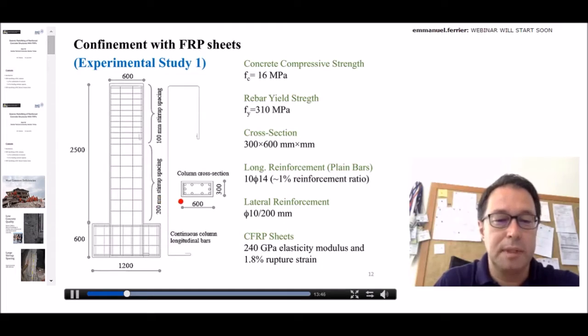So this is the configuration of the specimen. As you see, that's a cantilever column. The column dimension is 30 centimeters by 60 centimeters, and concrete strength is 16 megapascal. Yield strength of the main bars is 310 megapascal. I have already described the column cross-section sizes. We have about 1% reinforcement ratio in the longitudinal direction, which is 10 bars of 14 millimeters. And the lateral reinforcement is 10 millimeter bars at 20 centimeter spacing, which are the most critical areas.